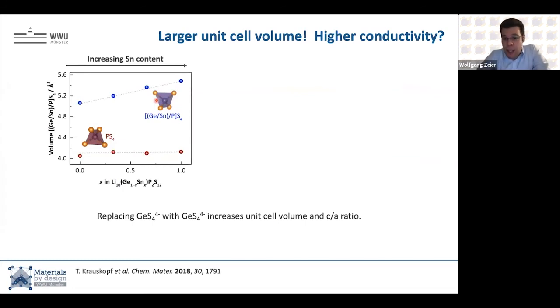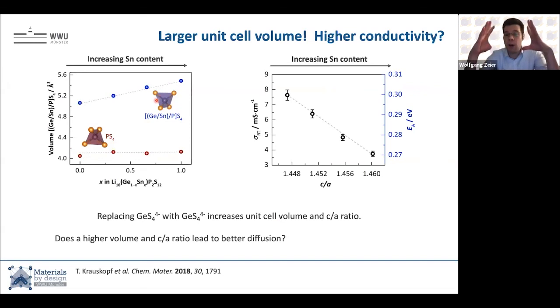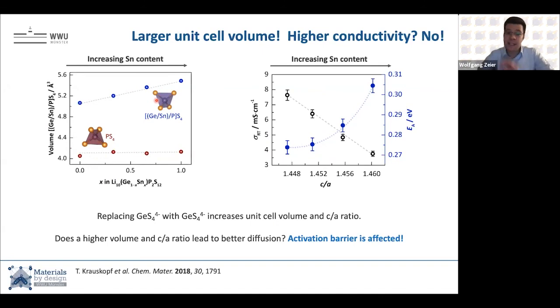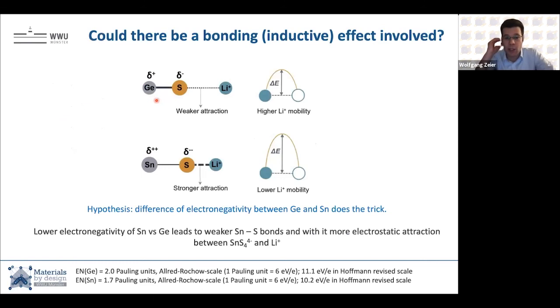How does that influence the transport? Well, we're pulling the unit cell apart, and the conductivity, from left to right with increasing tin content, decreases. And the activation barrier increases. And this is counter to everything that I just told you, that usually larger unit cells should give us a lower activation barrier. And so we really tried to come up with an explanation why this would be the case.